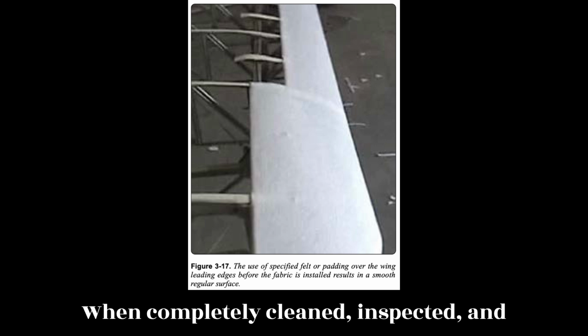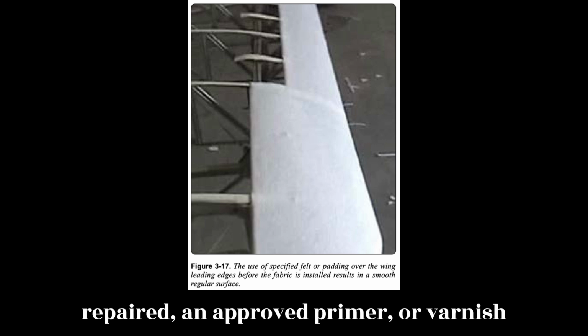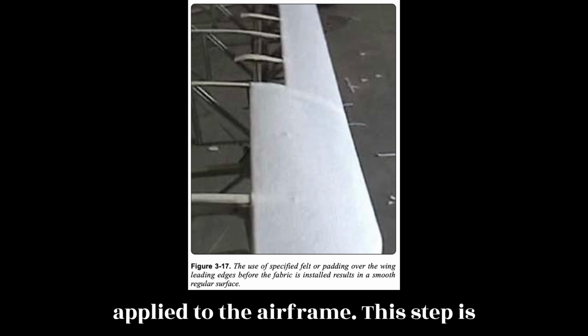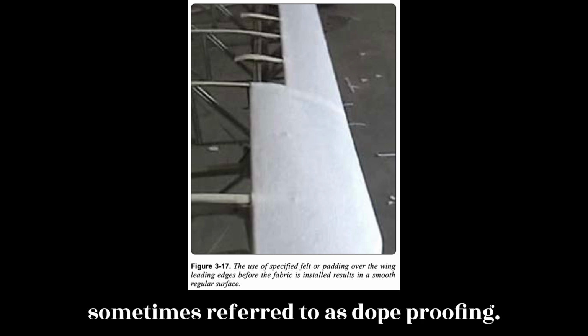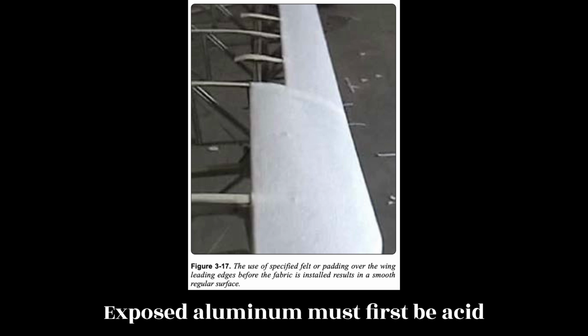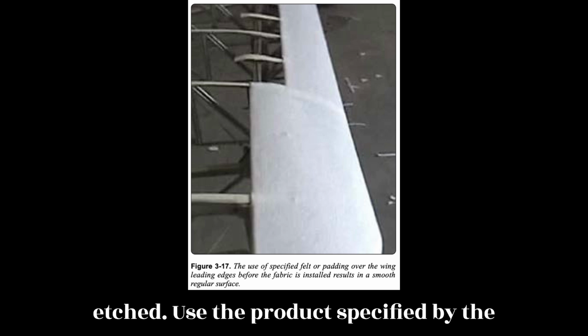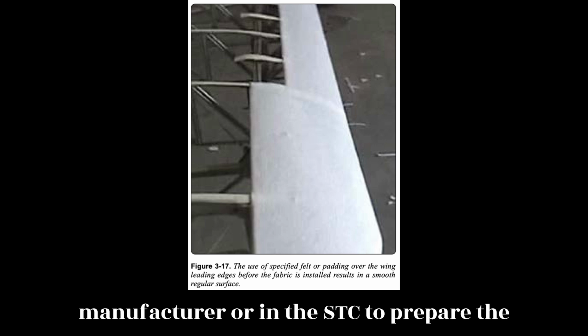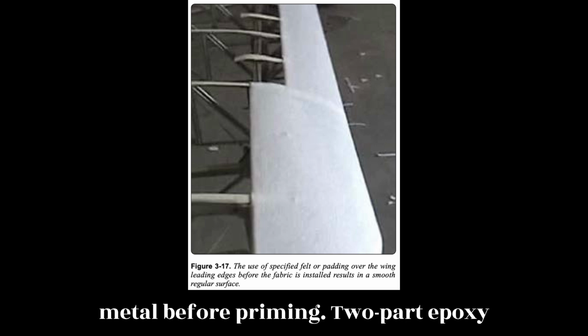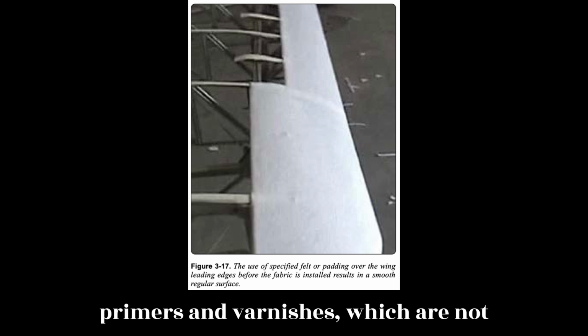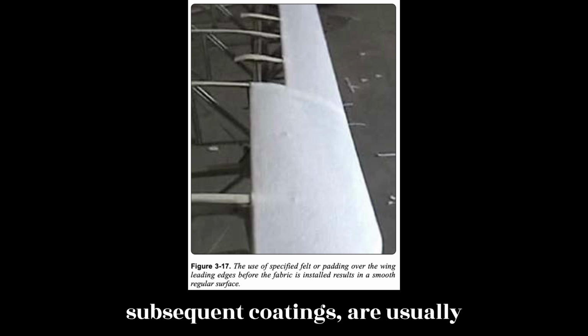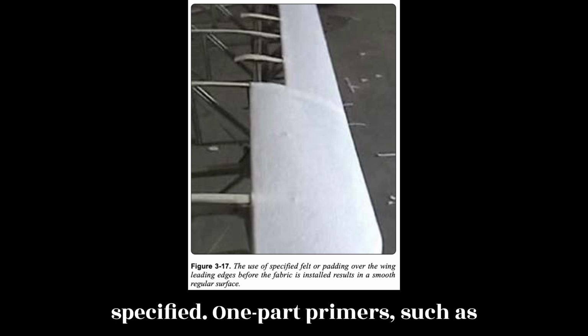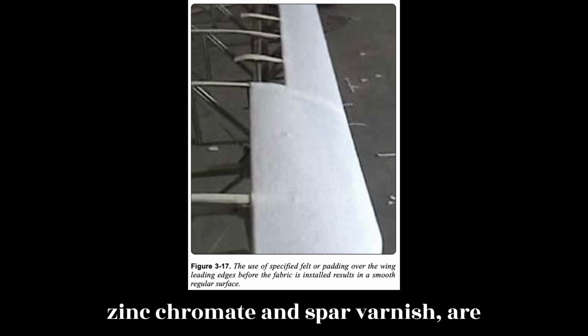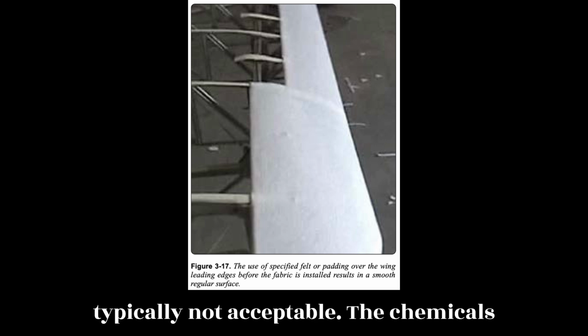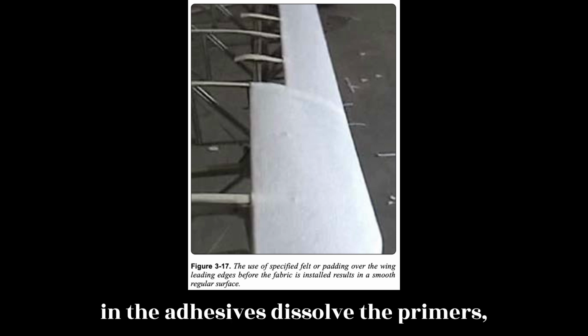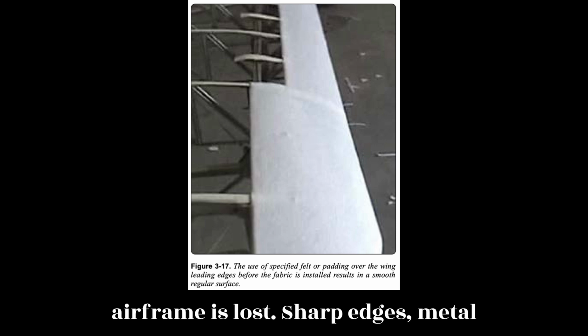When completely cleaned, inspected, and repaired, an approved primer, or varnish if it is a wood structure, should be applied to the airframe. This step is sometimes referred to as dope proofing. Exposed aluminum must first be acid etched. Use the product specified by the manufacturer or in the STC to prepare the metal before priming. Two-part epoxy primers and varnishes, which are not affected by the fabric adhesive and subsequent coatings, are usually specified. One-part primers, such as zinc chromate and spar varnish, are typically not acceptable. The chemicals in the adhesives dissolve the primers, and adhesion of the fabric to the airframe is lost.